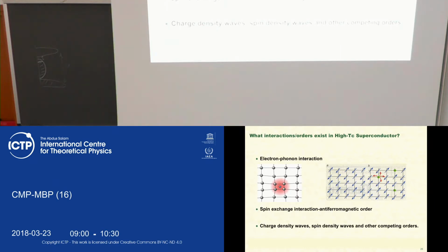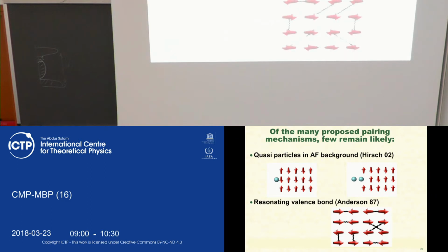And it was, as I said, clear that this is not phonon interaction, and therefore people started to look for the mechanism of how 2 electrons can be paired on the antiferromagnetic background. One of the ideas was to look for a mechanism based either on spin fluctuations or some resonances in the spin system, which then can mediate the superconductivity of these systems. And then Anderson came with a pioneering idea of the resonant valence bonds. This is a cartoon showing how single particle and 2 particles propagate in an antiferromagnetic background.